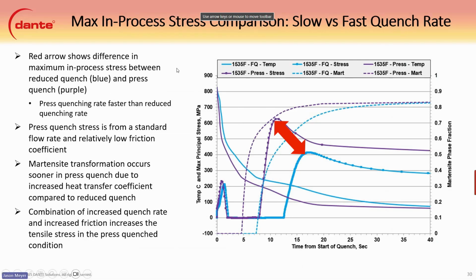And this shows, again, we can do the deep dive here with the stresses in the process. The red arrow shows the difference between the maximum in-process stresses between the reduced quench in blue and the press-quench in purple. The press-quenching rate is a lot faster than the reduced quenching rate, obviously, since it's reduced. And we can see that the martensite transforms really quickly through the process here, whereas when the martensite is transformed with the reduced quench, it's a little more gradual. You can see the slope is a little more gradual when it's being transformed. And this results in the quench rate and the increased friction resulting in the high tensile stress in the press-quench condition.